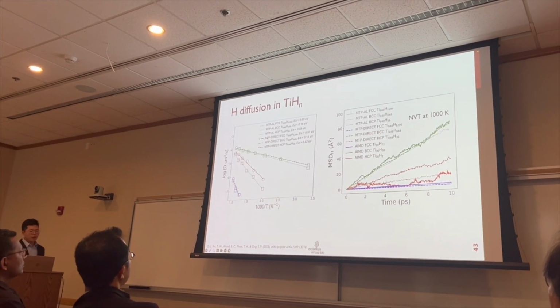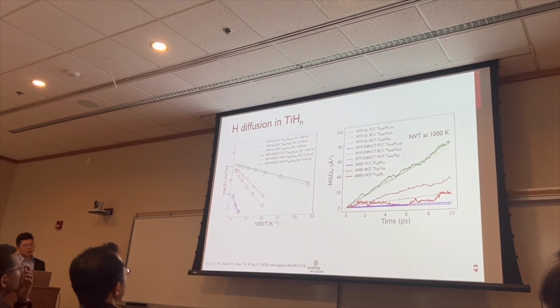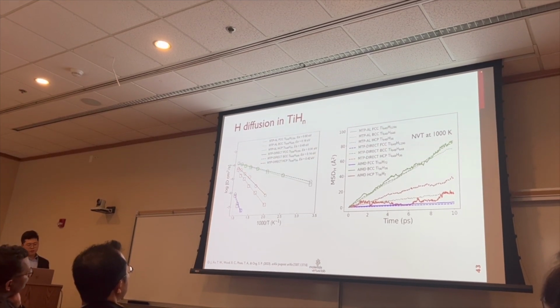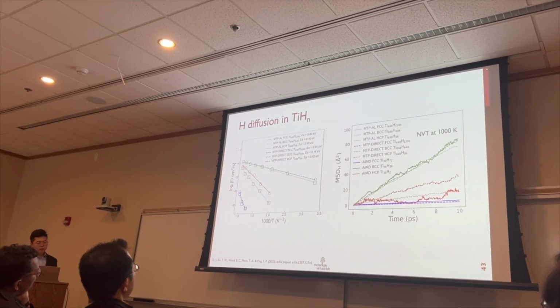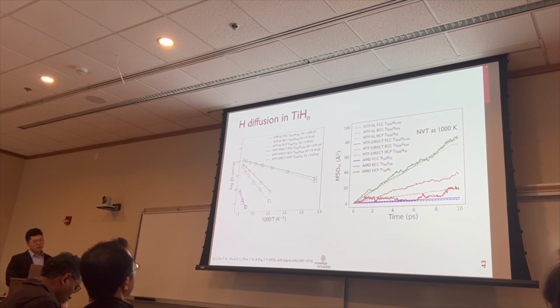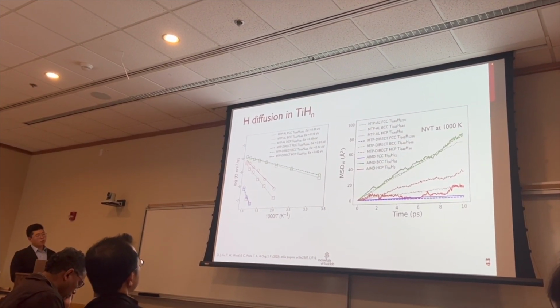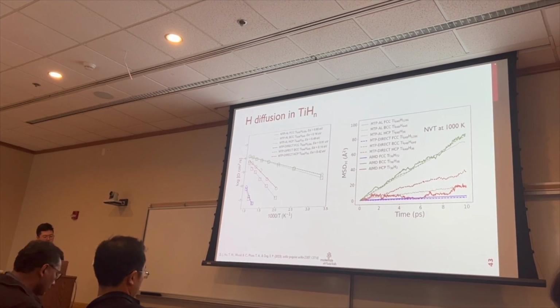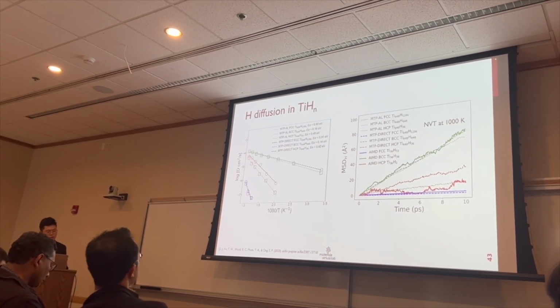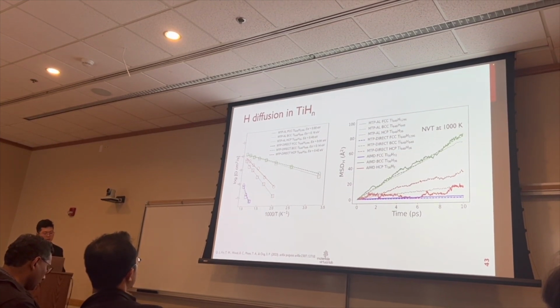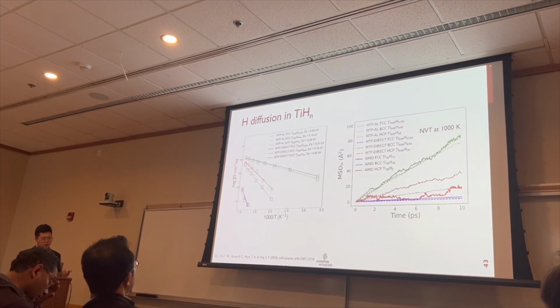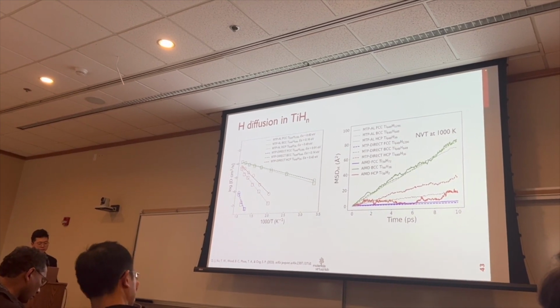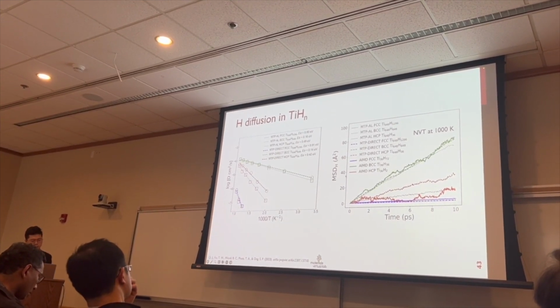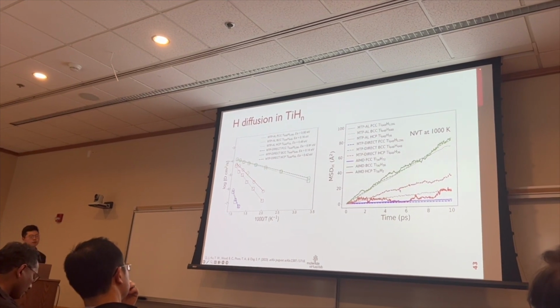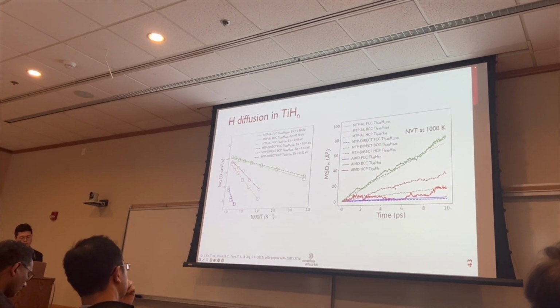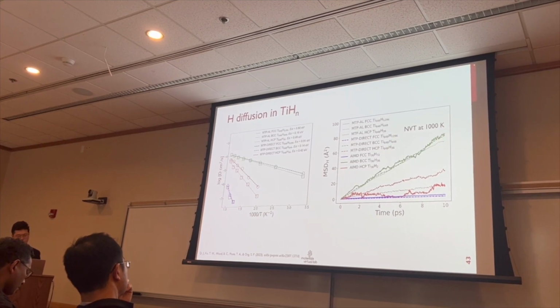Then we perform large-scale MD simulation to study the hydrogen diffusion in this titanium system. What we found, in the first plot, is that these two MTPs match very, very well with each other for the trend that hydrogen diffusion is fastest in the BCC system, while it is slowest in the HCP system. And in the second plot, we show that these two MTP models both get reasonable matching with the AIMD result at 1000 Kelvin.